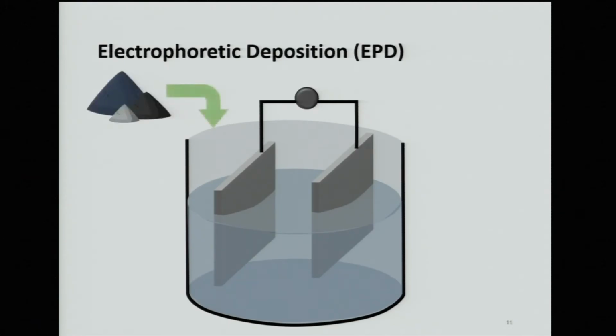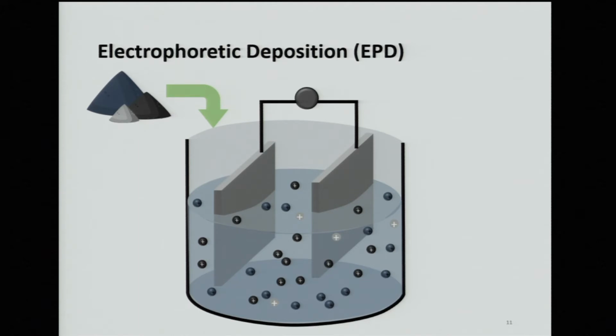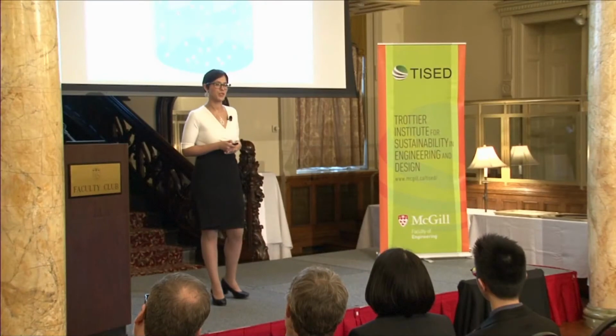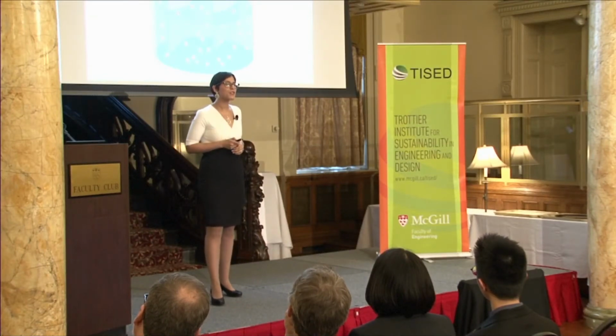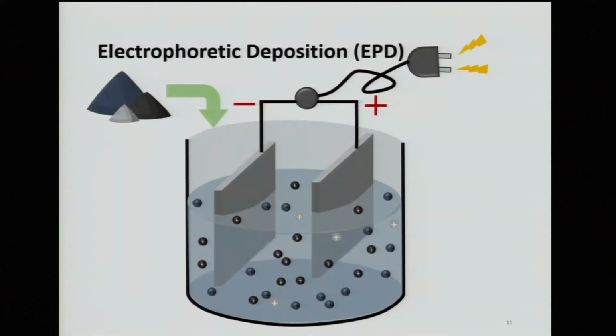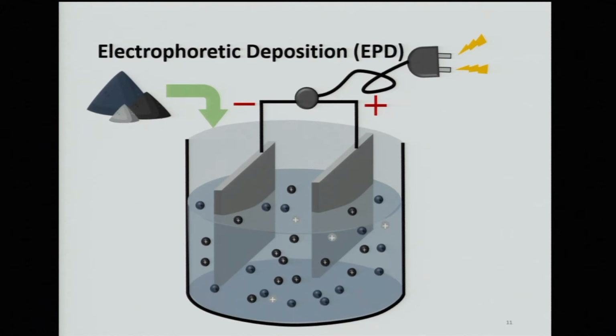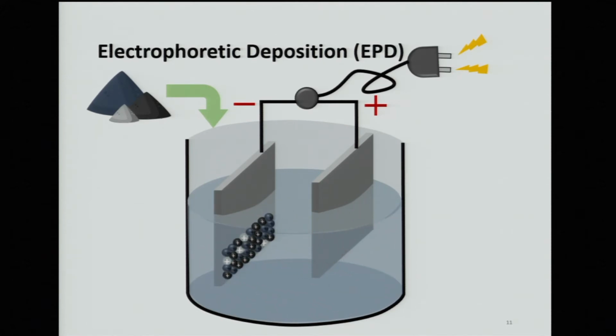Now, within this liquid, we place the lithium-ion material, the conductive material, and in some cases, a binder. And we mix vigorously to make sure that we have a very well-mixed solution. Now, we actually call it a suspension at this point because there are powders in suspension. And in suspension, these powders develop a charge. And whether they're negative or positive depends on the material itself, and it also depends on the liquid that we're using. If we then take the metal surfaces and connect it to a power source, it forces a charge to also develop on these surfaces. As a consequence, the powders will migrate towards the oppositely charged surface and deposit. This gives us the painted layer that we then use as an electrode.